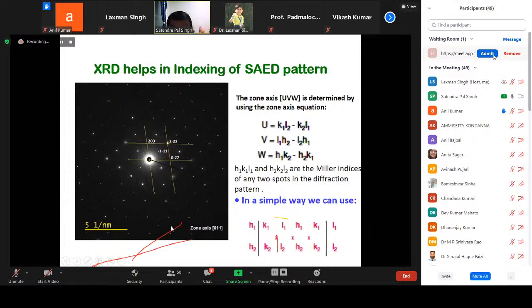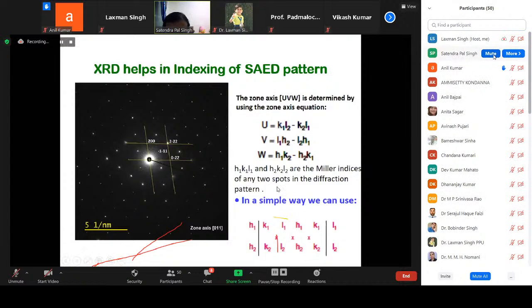In this TEM pattern, you get this diffraction spot along with this line. This line is very important. There are two ways to index this TEM pattern. First, you can use software like ImageJ. Then you can measure this distance and calibrate it to the scale bar, 1 per nanometer. All these diffraction spots are in reciprocal space, that is 1 by d spacing. So if d is larger, the spot will be closer. If d is smaller, it will be farther, because this is in reciprocal space.